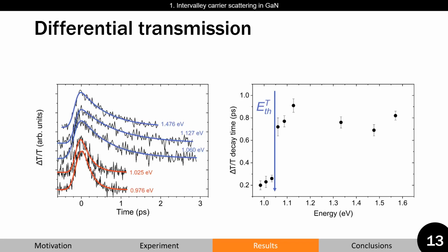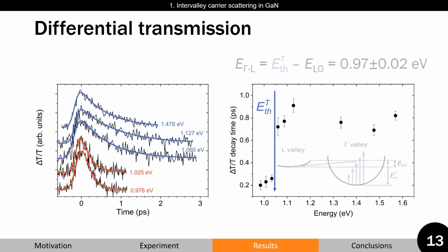Here one should mention that carrier scattering participates with the assistance of longitudinal optical phonons. Therefore, we can use a very simple equation by subtracting phonon energy from our measured threshold energy. Intervalley energy is experimentally evaluated. We also wanted to double-check this value, therefore an additional measurement was conducted.